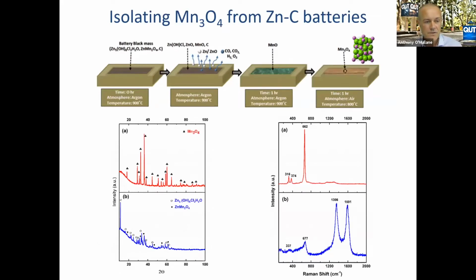One of the processes we did was to remove the battery material, and then we did a pyrolysis process. By varying the temperature and the atmosphere involved, we end up with a manganese oxide type material. The composition we got was manganese 3O4 as opposed to straight manganese dioxide. We characterized this with Raman and XRD to confirm the composition, and we showed that the initial material had carbon in it, but after we treat it, we don't have any carbon left, so we have a pure manganese oxide material.